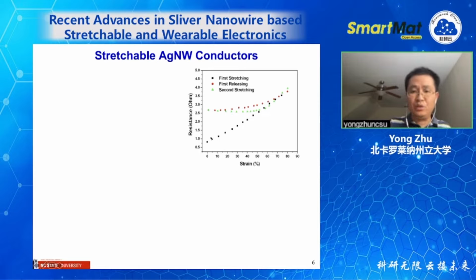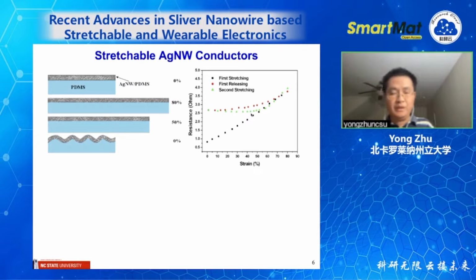Here I'm showing the resistance versus the strain curve. This is the first stretching, and the resistance increases almost linearly with the strain. Then when we release and stretch again, in the second stretch, the resistance is nearly constant. Again, that's what we wanted. But why are the second and the first so different, and why is the stretching and releasing behavior also very different? So we propose this mechanism.